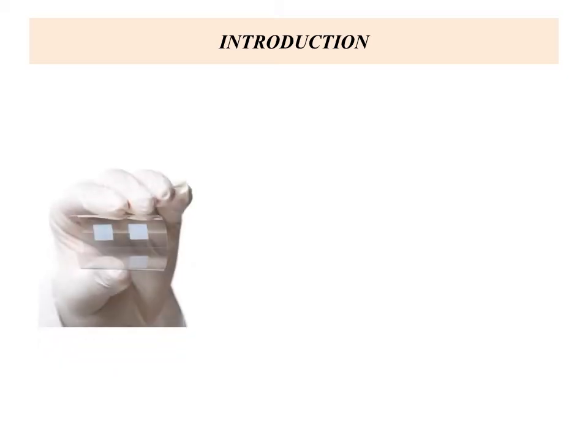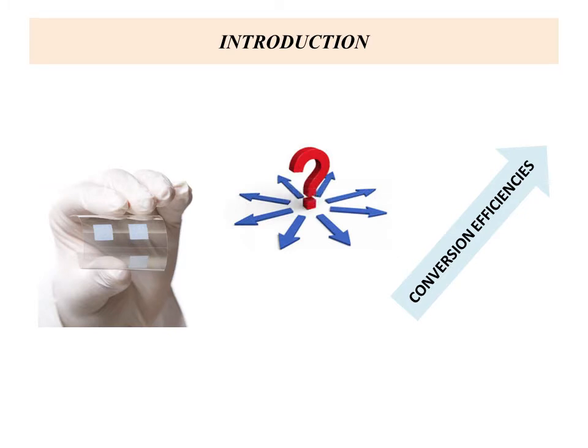Recently, flexible dye-sensitized solar cells have been developed by replacing the conductive glass substrate with a flexible substrate, such as conductive polymeric films for the working electrodes and the counter electrodes. This cell can be fabricated with low cost, lightweight, and less shape limitation. To develop flexible dye-sensitized solar cells, many groups have devoted their efforts to fabricating nanocrystalline titanium oxide film electrodes on conductive polymeric substrates as the flexible photoanodes. However, less attention has been paid to studying the flexible counter electrode.